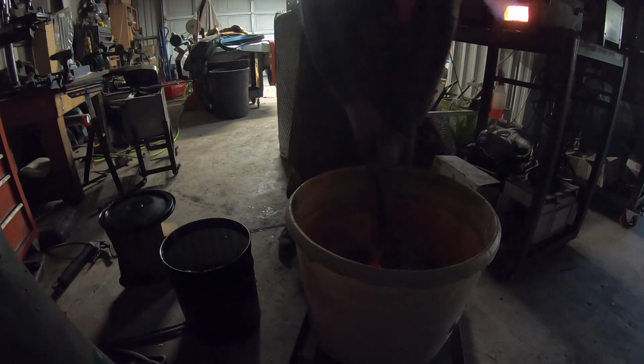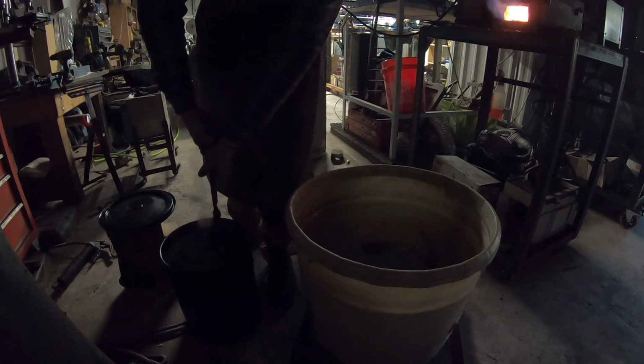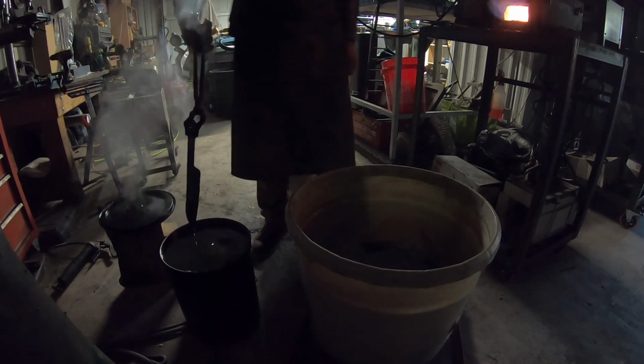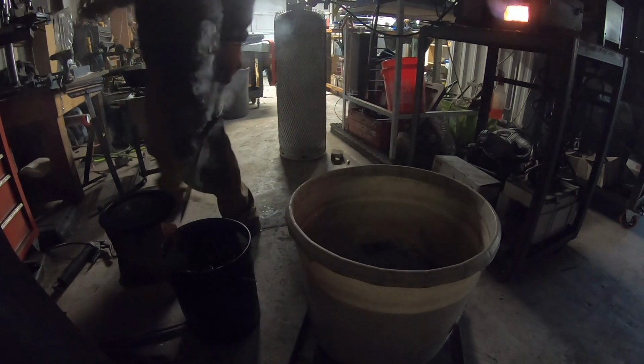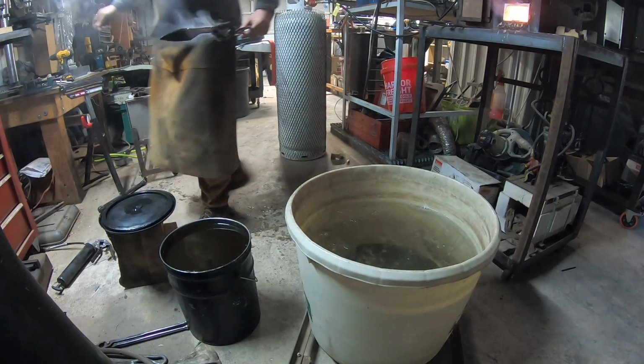Now, this doesn't actually help us until we heat it back up to critical temperature during austenitizing. Those dislocations provide renucleation sites for the new grains that form as the steel changes phases. And that is how cold forging helps refine the grain structure of the steel.